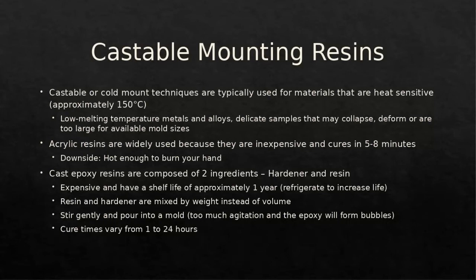But when you stir them, you're going to stir it gently, kind of like mixing pancake batter. You're going to kind of fold it over one another. You're not going to mix it all fast. You're not going to beat it like eggs. So you're just going to mix it around, folding it one over another for about 1.5 to 2 minutes, because you don't want to create enough agitation that'll form bubbles. The bubbles will then stay within your epoxy, and that is grounds for another area for debris to collect around your sample, and so it just ends up being a mess towards the end.